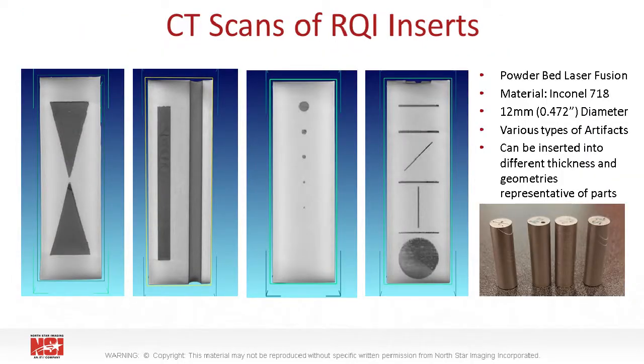These CT images represent some of the types of RQI inserts that we use to better understand the detectability of different shapes, sizes, and positions of unfused powder defects in Inconel 718 material in this case. The inserts are designed to be placed into parts or representative parts in locations that typically represent the worst case location for detectability. Even though some of the feature sizes are large, they can still be very useful in representing, for example, trapped powder within a part.